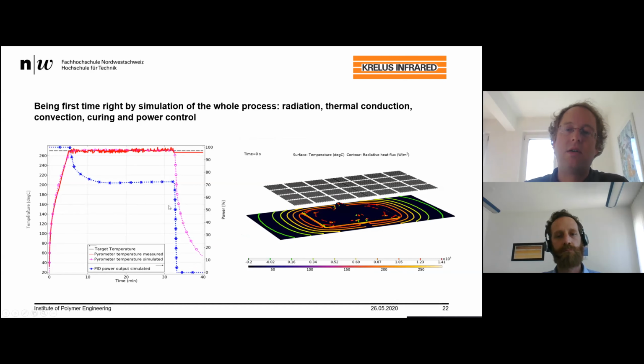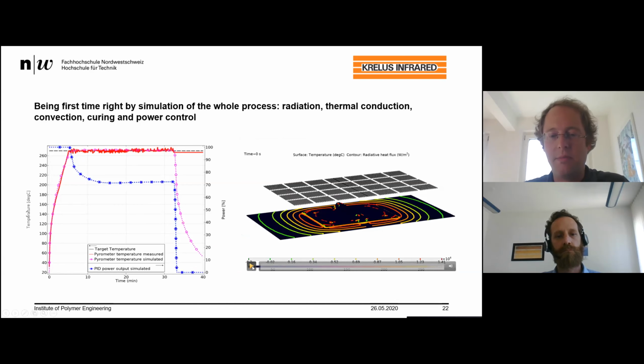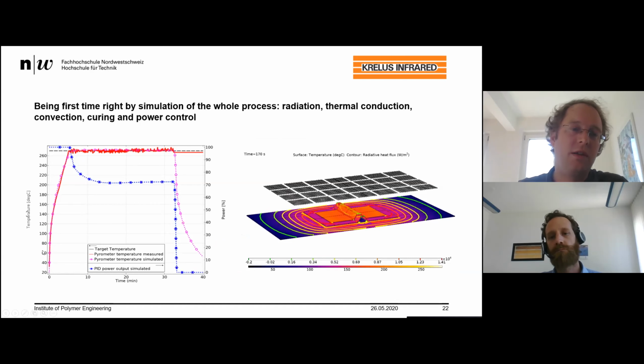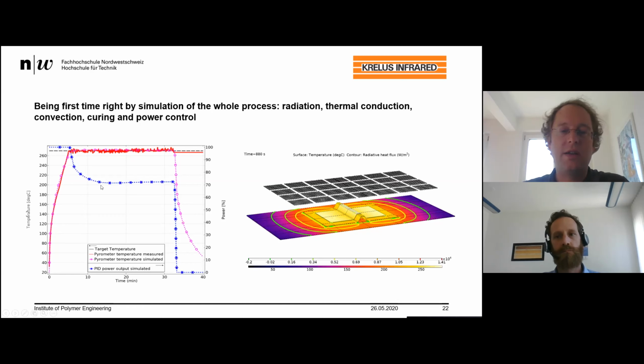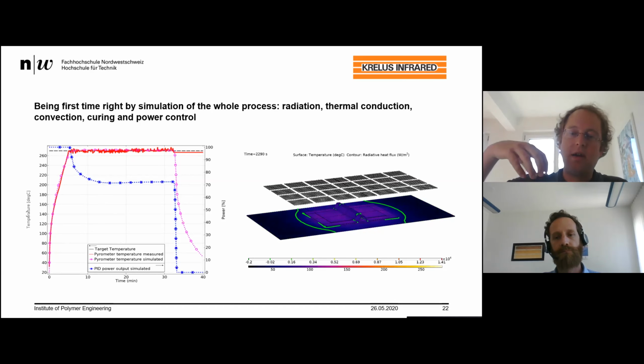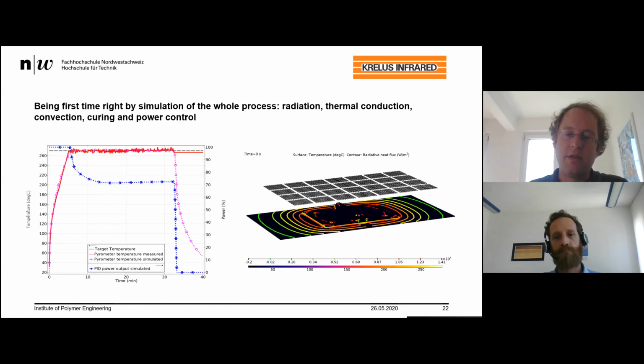And now I want to give you a little bit more insight. So here we compare the measured temperature of the pyrometer with our simulation, which fits really well. And the blue line, as you can see here, is the PID power output, which we simulated. So in the first part, the system applies 100% power, and then it reduces to nearly 70%, and it's just applying heat when it's necessary. So you have a constant heat flow through the part, through the setup. On the lower side, a cooling is applied. And this enables you to react to the process itself.